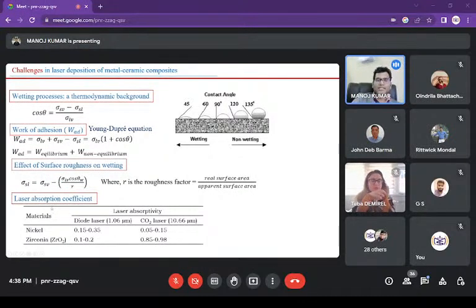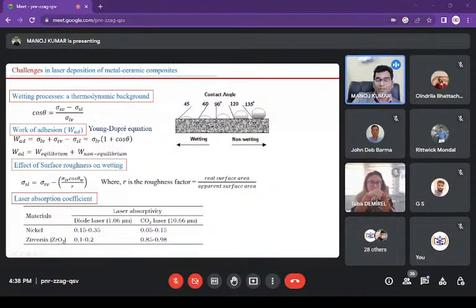And the second problem is that the laser absorption coefficients of the materials are different, as I said. So nickel, which is a metal, has a very good laser absorption of about 15 to 35%, whereas zirconium oxide has only 10 to 20% laser absorption. So when it doesn't absorb the laser, and if you keep increasing the laser power, it doesn't serve the purpose. So laser cladding becomes difficult, and if you go on increasing the power, the metal will start evaporating. That is again an issue. So having an optimized zone of laser processing is very important. We have to do lots of trials to come to a narrow window of processing parameters.